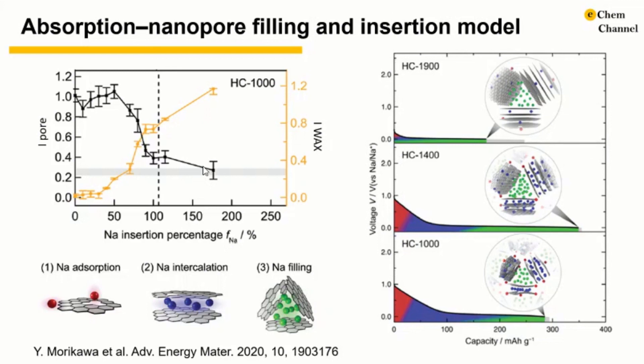The relative scattering intensity from the nanopores observed by SAXS always shows an opposite intensity change to the WAXS intensity. This result indicates that the origin of the new signal in the WAXS profile is the atomic correlation of sodium in the nanopores, meaning there is a presence of dense sodium assemblies in the nanopores. Thus, the authors suggested that the plateau capacity is contributed by both sodium ion intercalation and the nanopore filling mechanism. The capacity ascribed to sodium filling into nanopores does not show monotonic variation with heating temperature — a maximum is achieved in hard carbon heated at 1400°C, and this greater nanopore filling mechanism may well explain its highest capacity among all samples.